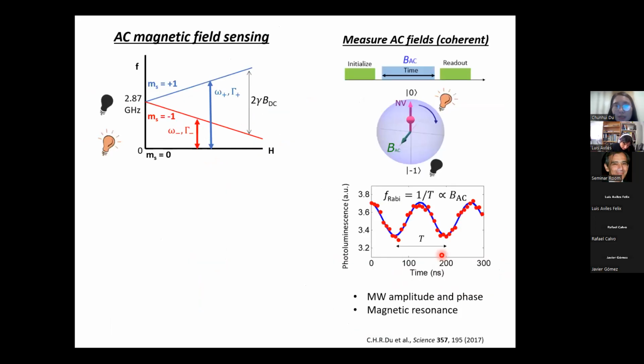And in addition to static field and temperature, NV center is also sensitive to microwave field. For instance, it's sensitive to coherent microwave field. And when a coherent microwave field is applied at the NV electron spin resonance frequency, for instance, at the frequency of the 0 to -1 spin transition, if we vary the duration of the microwave field, the NV spin will, in the rotating frame, rotate about this external applied microwave field periodically, so it will rotate between 0 and -1 state.